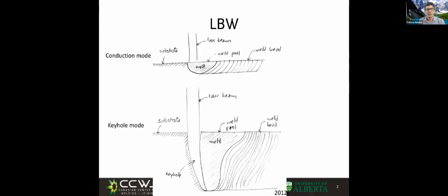Now, the interesting thing with lasers, and it's also true of the case of electron beams, is that if we have too high power, we don't have a plasma jet, because in this case, there is no plasma and there is no electrical current circulating in a fluid. But what happens is we have local evaporation, and this evaporation essentially drills down into the base metal. And as it drills down into the base metal and the metal evaporates, it causes a hole. That's what we call a keyhole.